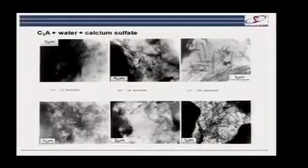Now, what's important to see here is if you read textbooks, and quite honestly, I would say to people most of the time don't read textbooks because there's more things that are wrong in textbooks than right. Because if you read textbooks, this tells you that the reaction of C3A slows down because you form a shell of ettringite. This is nonsense. You don't form a shell of ettringite. You see, you've got these little ettringite crystals here, and how can this little ettringite crystal be blocking the reaction of that C3A with the water?